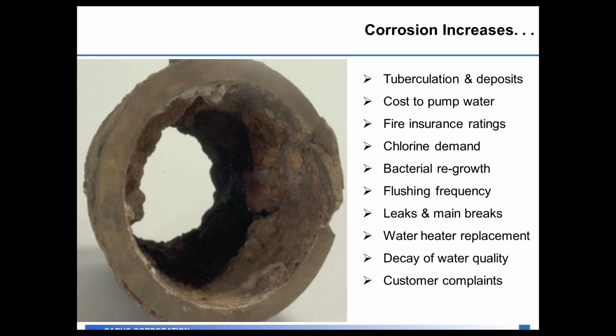Obviously, leaks and main breaks would tell you you have severe issues with corrosion in your distribution system because now the pipe is actually corroded so much that it's caused a crack and you're leaking water out into the ground, and you have to do replacement of those. Overall, though, all these things on this list lead to a decay of water quality that causes the water that leaves your plant, which is crystal clear and tastes great, by the time it gets to the consumer, it's picked up color, it's picked up taste from that tuberculation and scale, and the customer is calling you to complain that the water doesn't meet their expectations.